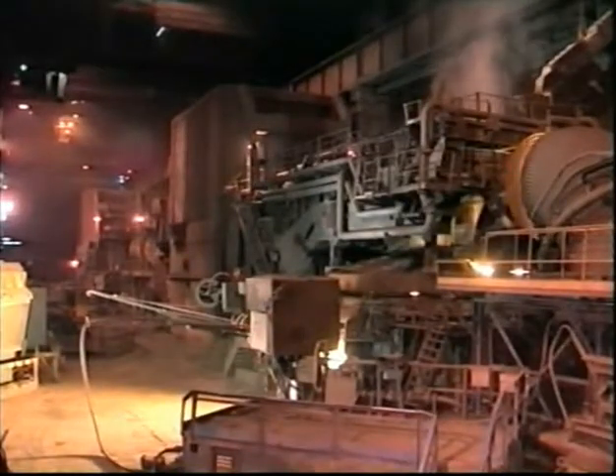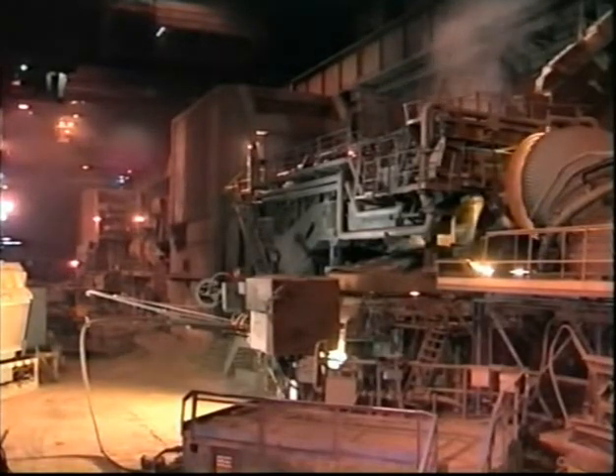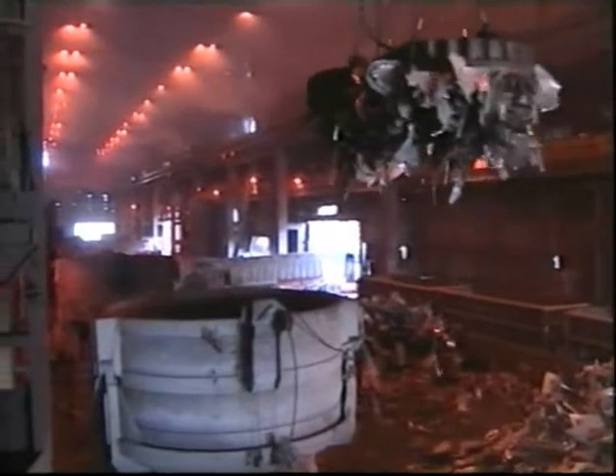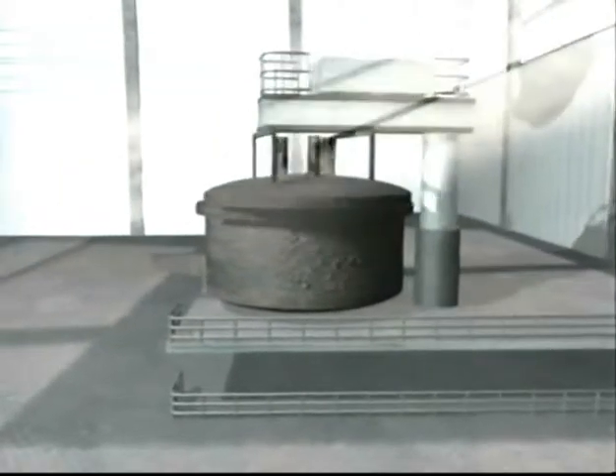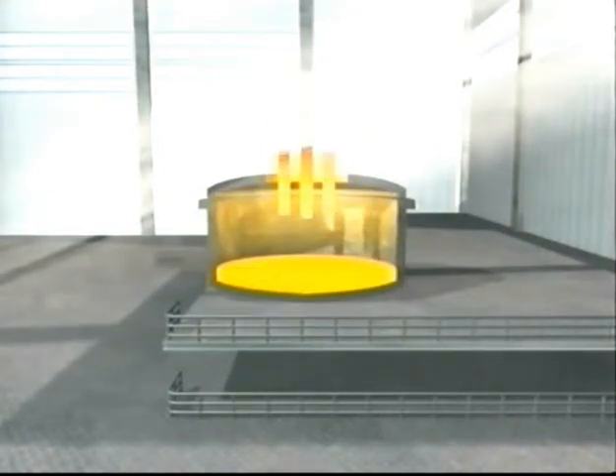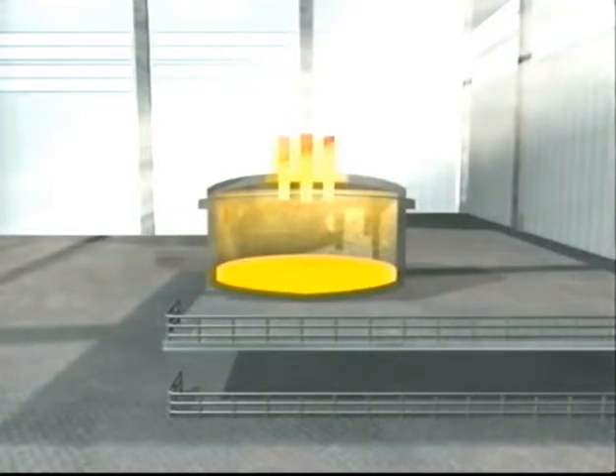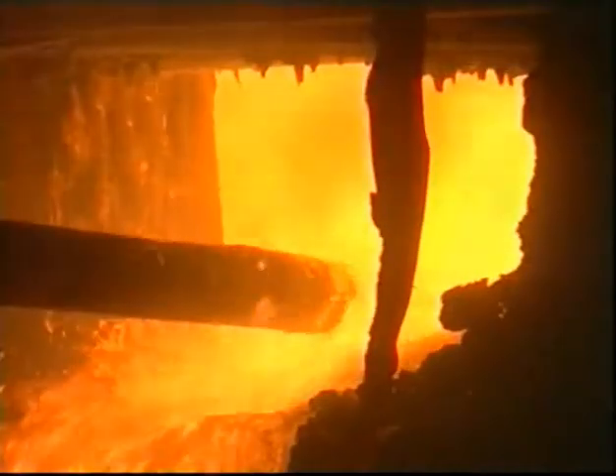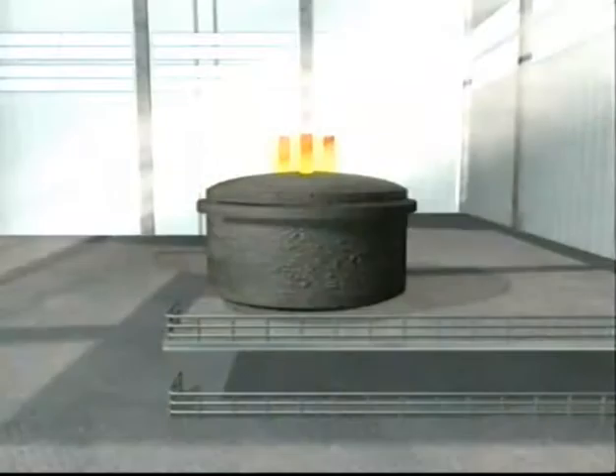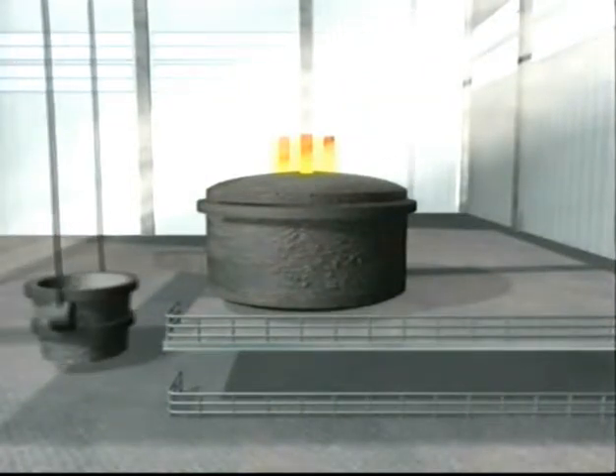The other main method of making steel is by means of the electric arc furnace, or EAF. The EAF process predominantly uses cold steel scrap, making it one of the world's largest recycling processes. EAFs make up to 150 tonnes of steel in a single melt in less than an hour. The furnace is filled with recycled steel scrap, the roof is then swung into place and three graphite electrodes are lowered into the furnace. A powerful electric current is passed through the furnace, an arc is created and the heat generated melts the steel scrap. Lime and fluorspar are added and usually carbon and oxygen are blown into the melt. As a result, impurities in the metal combine to form a slag. The steel is sampled and analysed and once it reaches its correct temperature and composition, it is tapped off.